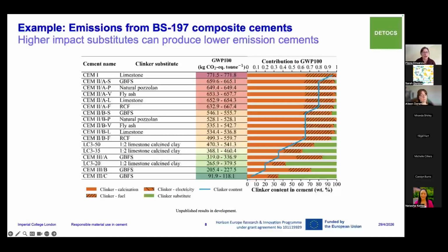And just an example here is some mix designs that we've calculated compared to a high clinker CEM1 cement, down to about 50% and lower clinker cements made with limestone, calcined clay and blast furnace slag. So what we see from this is that the degree of substitution is more important than the specific material used. So higher footprint substitute materials can produce lower footprint cements if they allow more clinker to be replaced.